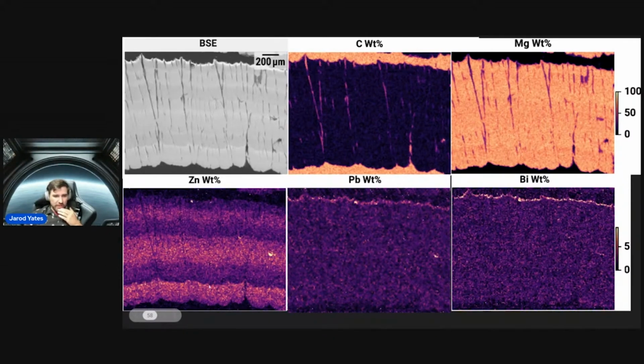We have a really bright layer of zinc and then a dispersed layer of zinc, a really bright layer of zinc, a dispersed layer, and then a really dim layer of zinc. Also important is this bright spot that you see for the zinc and for the lead. Those are the zinc-lined lead microspheres that have ruptured, which is why you're seeing it show up so brightly in those areas. Over here, they claimed in the error report that these vertical lines might have been some carbon-based binding agent. I don't know enough to say for sure whether that's accurate.